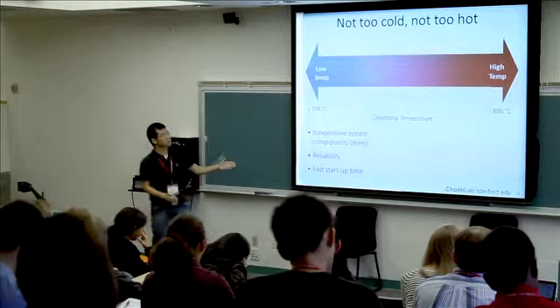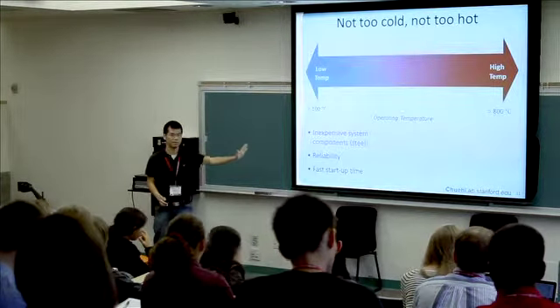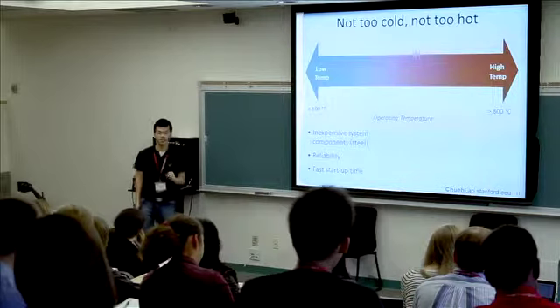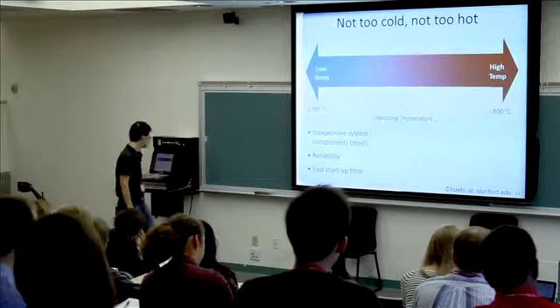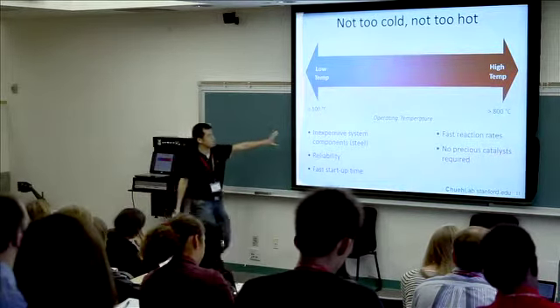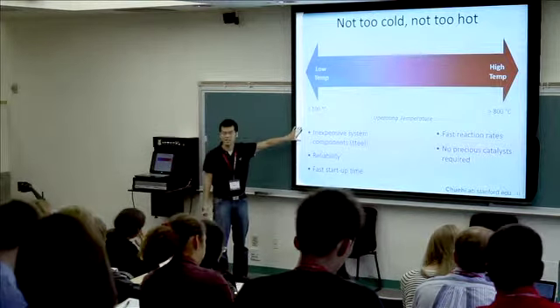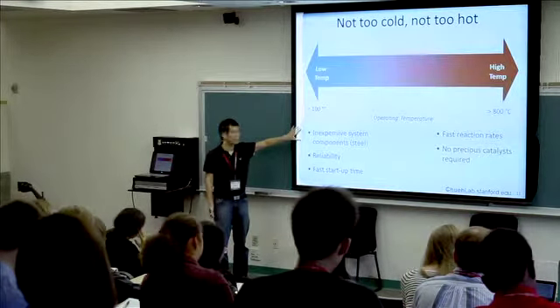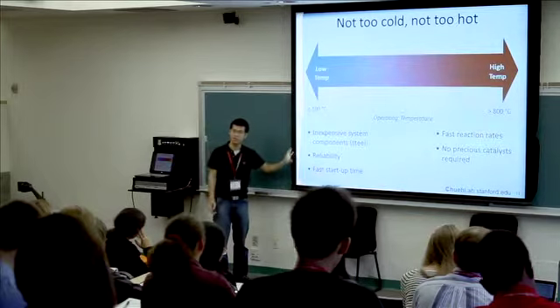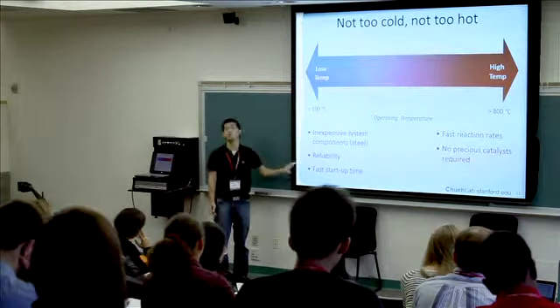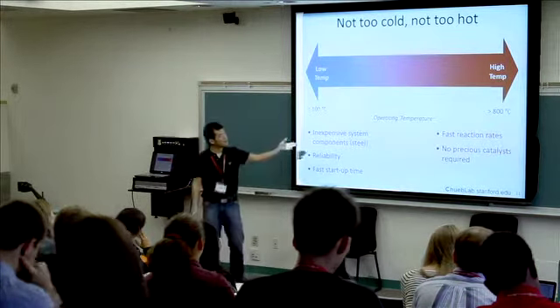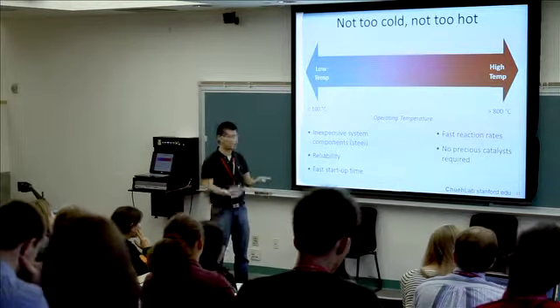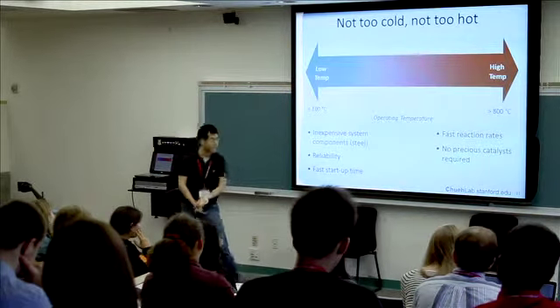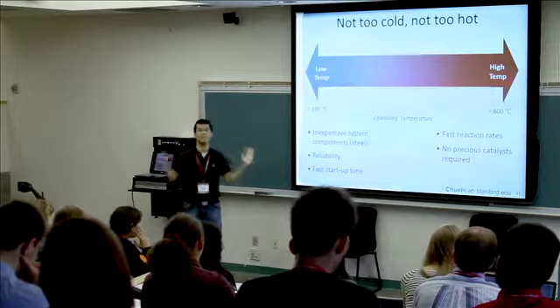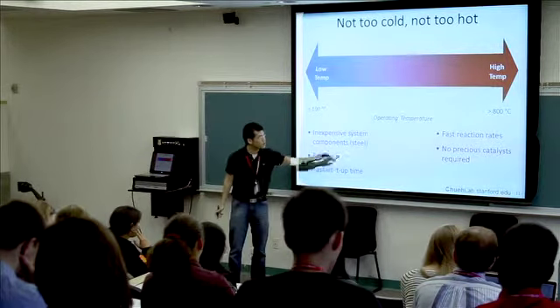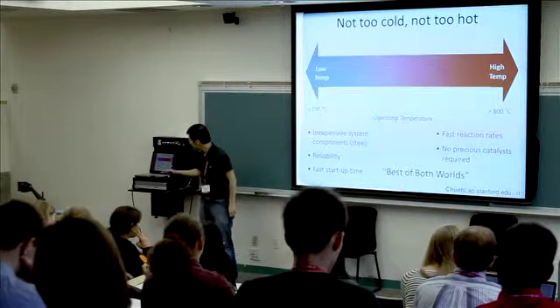On the Bloom Boxes, it's on the high temperature side. So it runs at about 800 degrees Celsius. That's pretty hot. So you have all these problems. It's expensive because you have to have a very expensive enclosure to hold it in. It's less reliable because the material tends to degrade, and the startup time is very slow. But of course, at the high temperature, we have the following benefits. The reactions, as I said in the first slide of my talk, are very, very fast. It's enormous. You don't even need platinum. Right? So what we want is to have the best of both worlds.